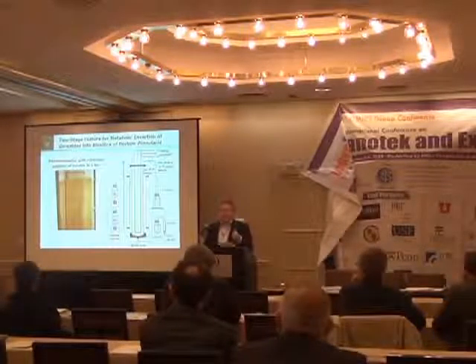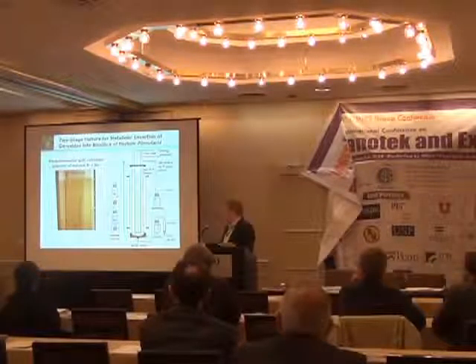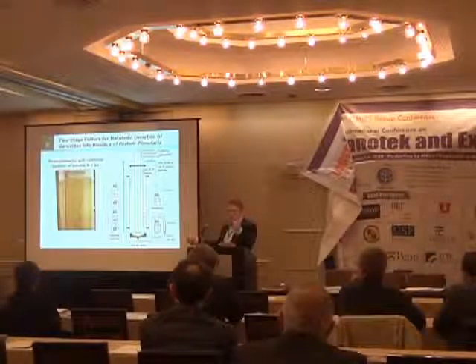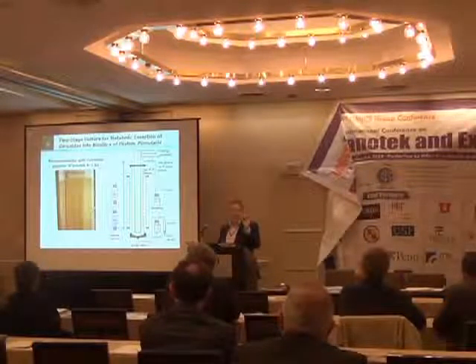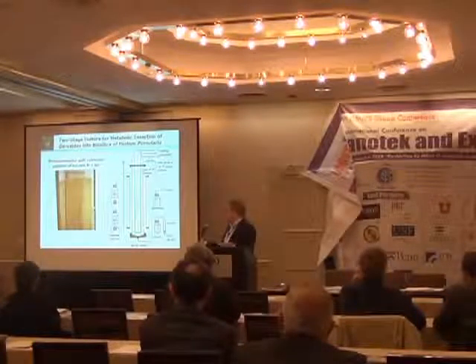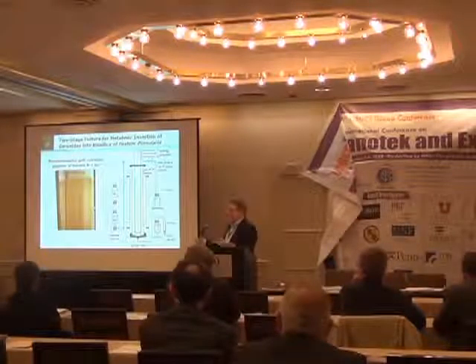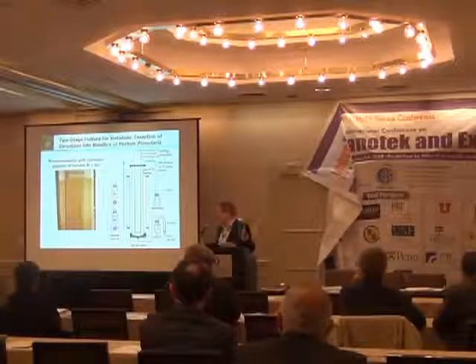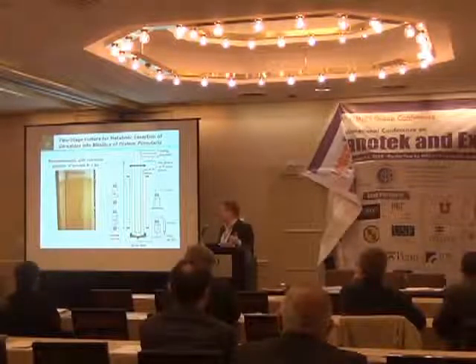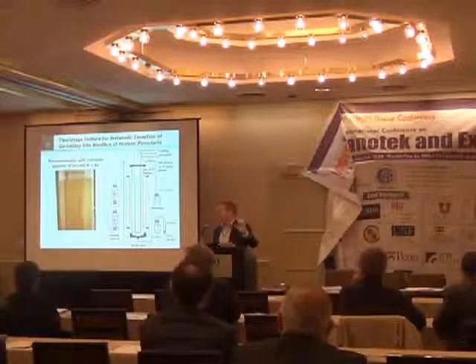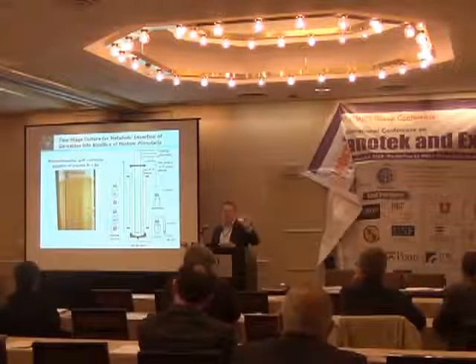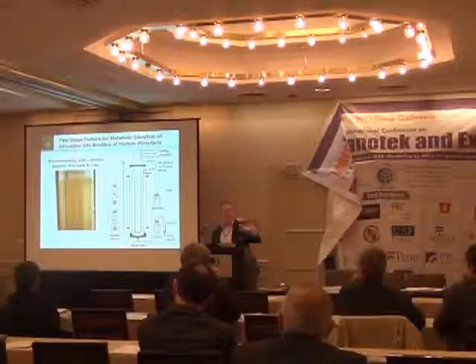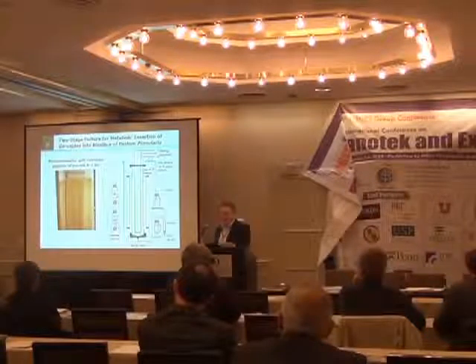Here's where the biology part comes in. Here's the cell suspension culture of those microscale organisms — about one cubic centimeter contains over a million of them, and they're identical. We use an externally illuminated bioreactor to cultivate these organisms because their photosynthesis requires light as an energy source and carbon dioxide as a carbon source. Since they have inorganic-based shells, we also do a programmed feeding of dissolved silicon and dissolved germanium, and the organisms take up these precursors in the soluble state and then fabricate nanostructured materials from them.